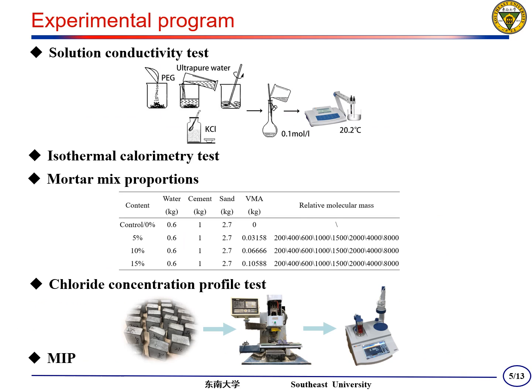The experimental program is divided into 5 parts, corresponding to 5 explorations, including solution conductivity test, isothermal calorimetry test, mortar mechanical property test, chloride concentration profile test, and MIP.